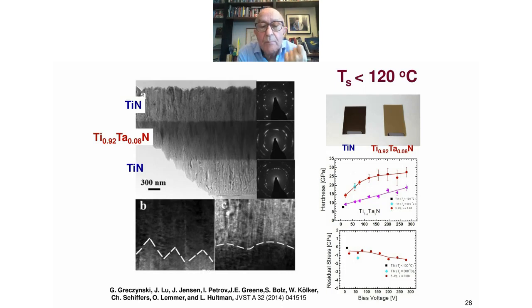So the mass of the bombarding ion really plays a key role. And if you look at the stresses in the films, up to 150, 160 volts, the stresses are nearly zero. And even if we go higher, they're below 1.5 or 2 gigapascal. So we have achieved low temperature growth of hard and dense, low stress ceramic coatings, which, in addition to saving energy and time during deposition, also permits depositing such coatings on temperature sensitive substrates, like aluminum, magnesium, plastic, alloys. So, next slide.